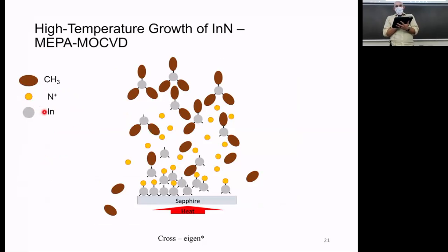So now we can go ahead and just dump all of this material into the reactor at the same time, and now I don't need to worry about breaking apart my ammonia, which it turns out ammonia is actually one of the biggest problems to growth at lower temperatures. Ammonia needs high temperatures in order to break apart, but since we don't have high temperatures for indium nitride, we had to figure out another source of nitrogen. And we solved another problem by doing that too.